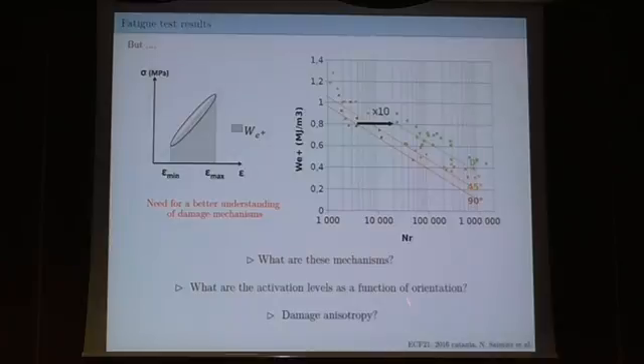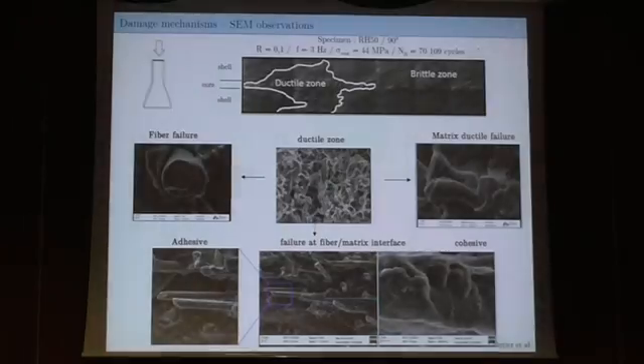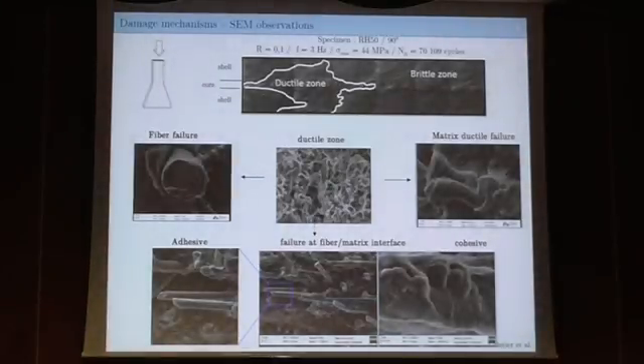But if you look more closely at these results, you can see that you still have a mismatch between the 90, 45, and 0-degree specimen. So there seems to be something behind, which is the anisotropy of the material that should be considered. So the question is, what are these mechanisms, what are the activation levels of these mechanisms, and do we have damage anisotropy? So what we did is, like everyone, we are looking at the SEM, we are doing some observation